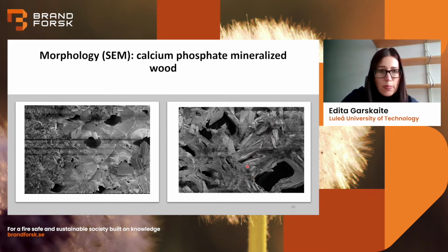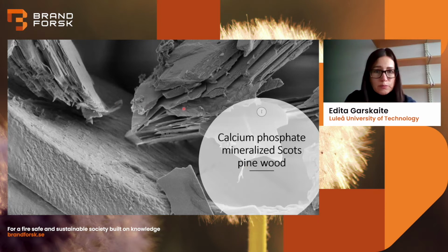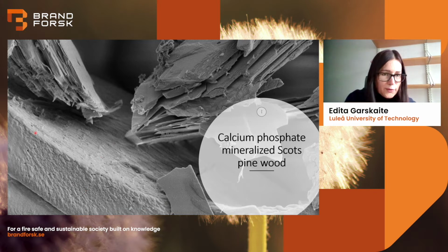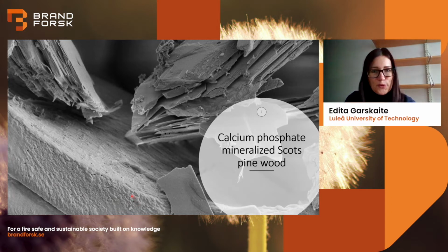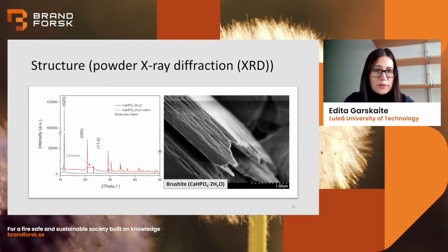And actually, these plate-like crystals, here is a closer look at them. You see it's very nicely attached to the cell wall, and the cell wall is so smooth, showing that it's a different composite material. So actually, this plate structure indicates that we have the mineral brushite inside the wood matrix. So brushite has in its structure 2 molecules of water.